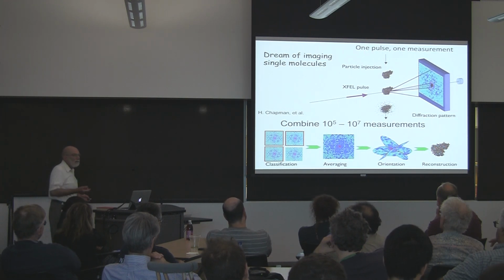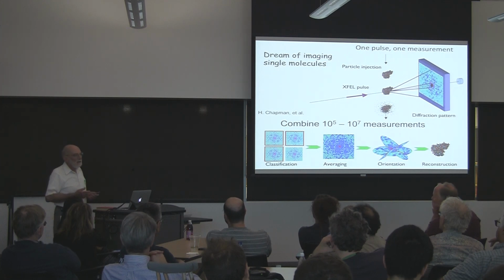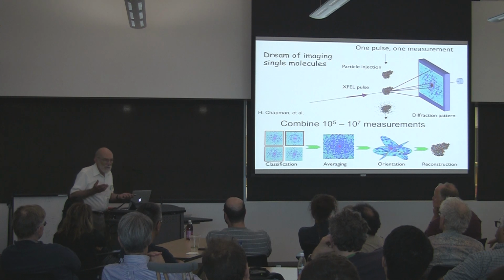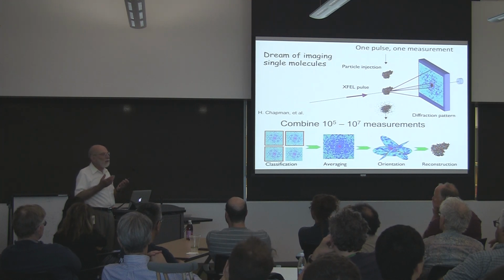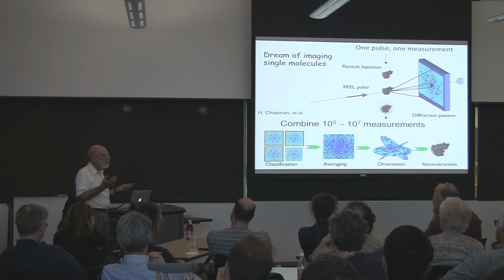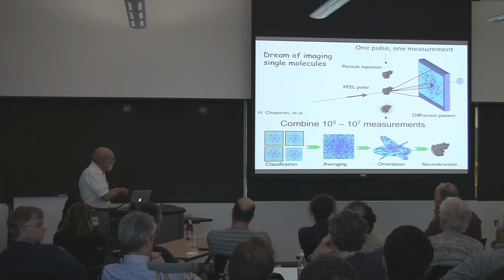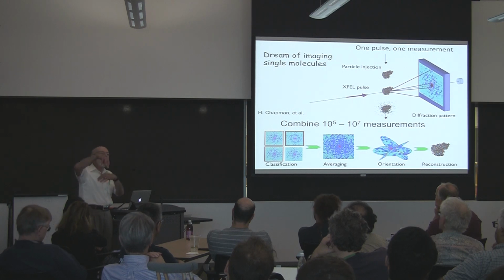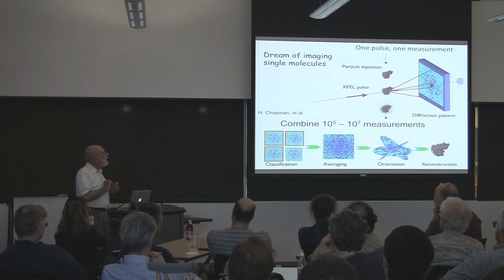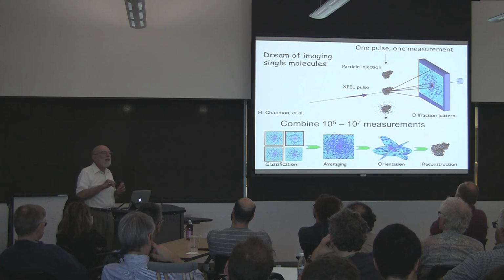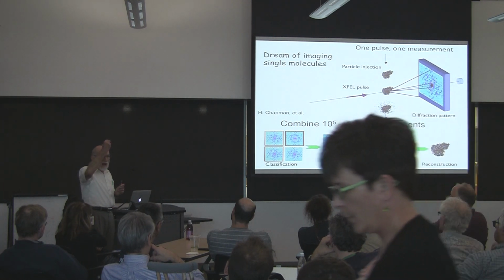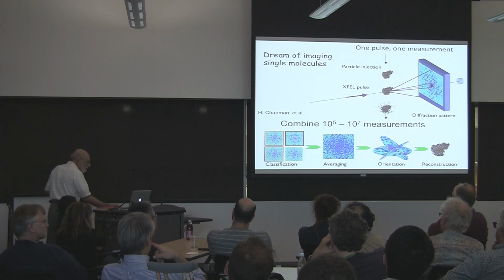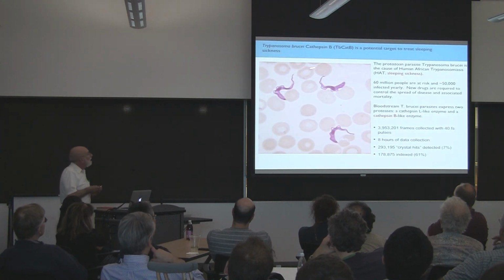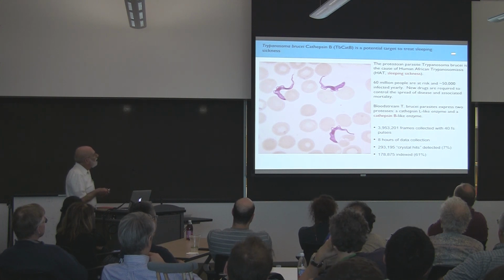Now, as it turns out, this dream, as of today, is still a dream. People have not been able to collect diffraction patterns at free-electron lasers intense enough to be able to classify them and find out what the orientation is. However, what people found out is that in many cases, if you cannot get one molecule, you can get nanocrystals of some materials. And to me, the most compelling example is the nanocrystals of cathepsin B, which are involved in